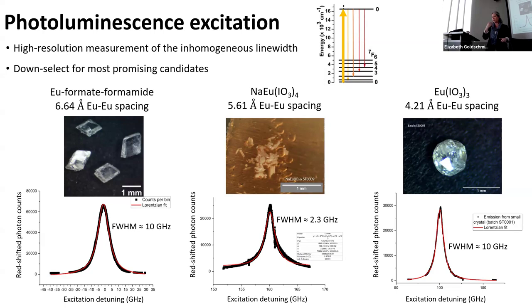We tried to grow this. We succeeded. We made these little tiny needles, and it actually has an even smaller inhomogeneous line width, which is nice. But when we grew this, we also accidentally grew this, and it was actually nicer and bigger than the crystals. And it also has a reasonably nice inhomogeneous line. So this is where we are now. We're looking at these three things, trying to understand why some of our samples are better than others.